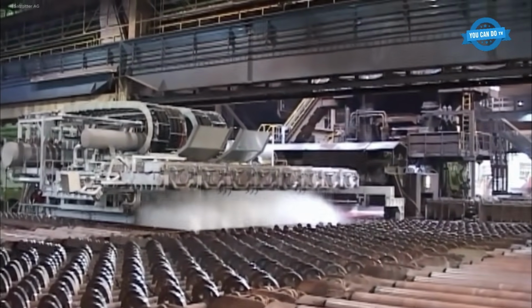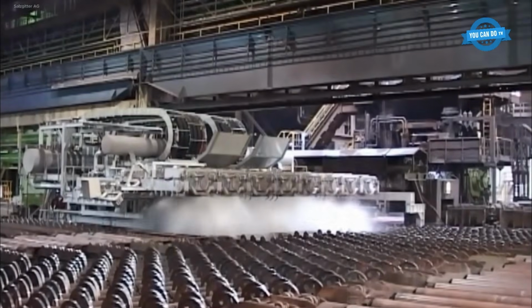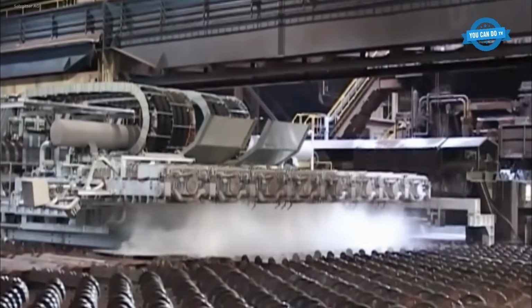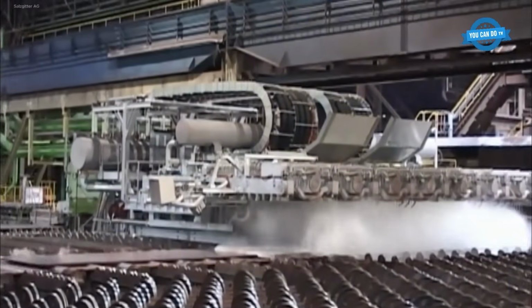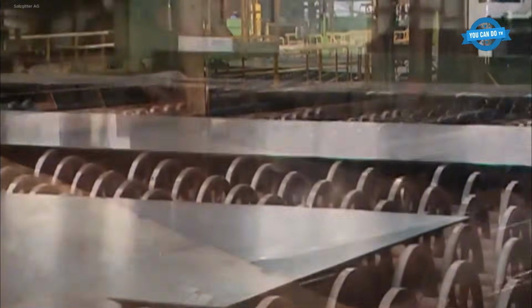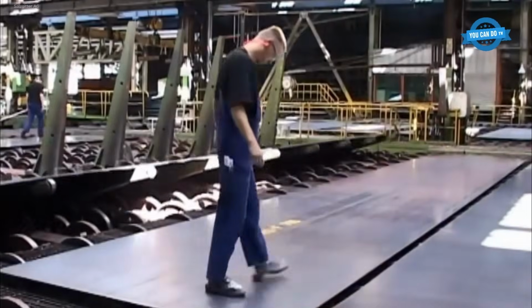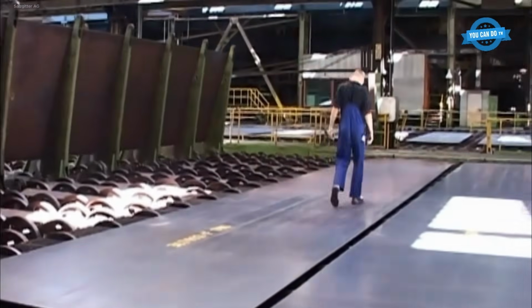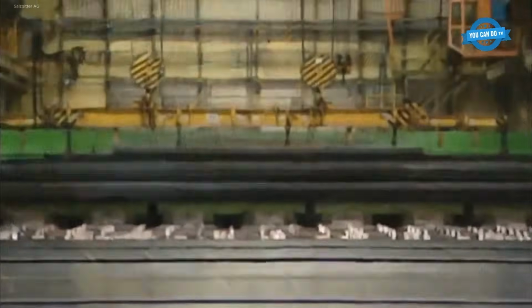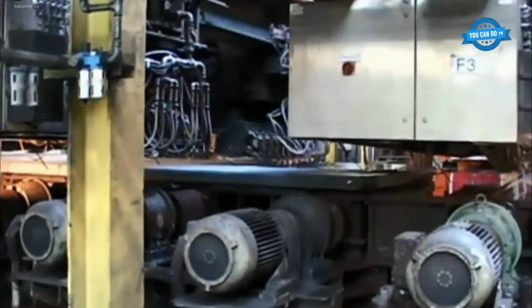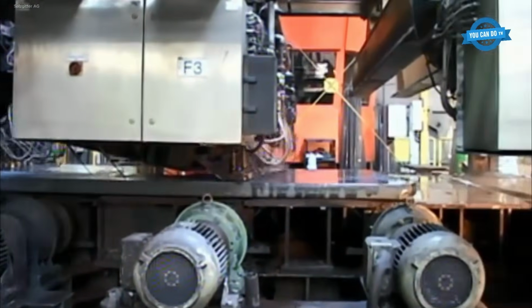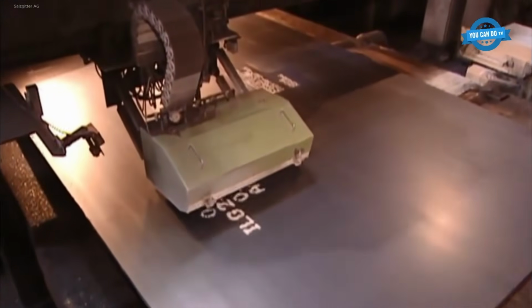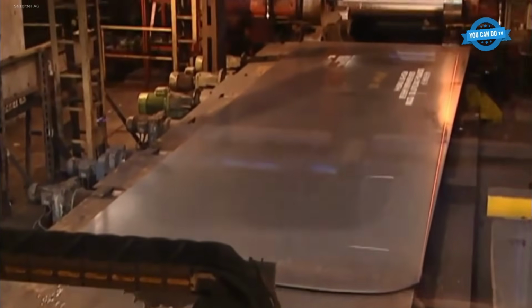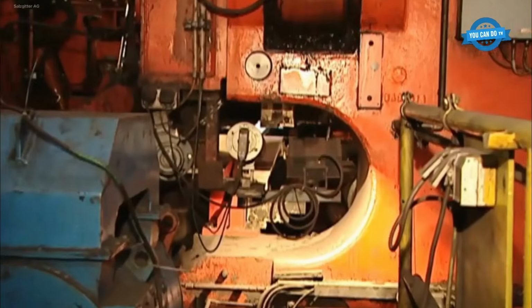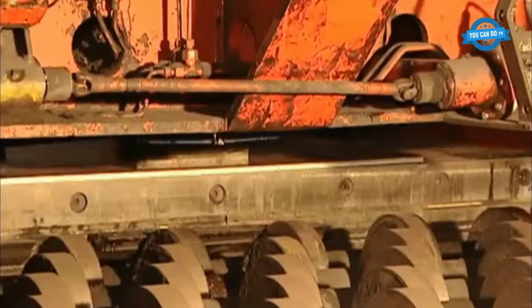Ilsenburger operates a sophisticated testing laboratory featuring CNC machines and low-temperature impact testing down to -196 degrees Celsius. Spectrometry, thermal analysis, and electron microscopy confirm alloy composition and microstructure quality. The production range includes normalized, annealed, or quenched and tempered plates, with water quenching units ensuring consistent strength and toughness. Ilsenburger also offers surface conservation, edge milling, and precision cold straightening.